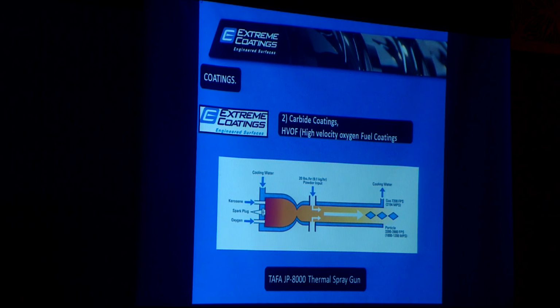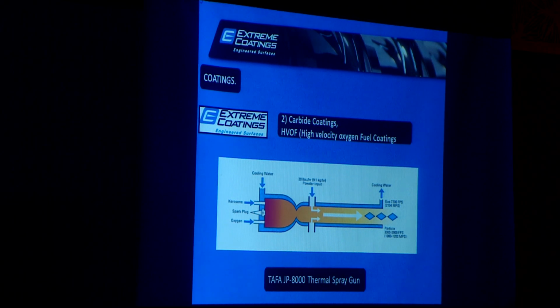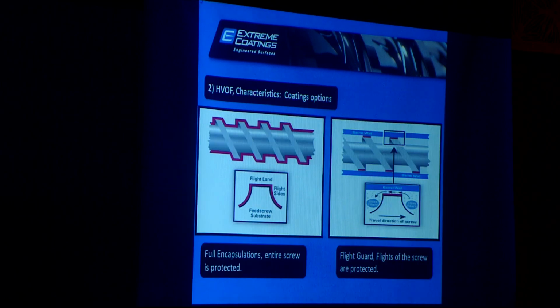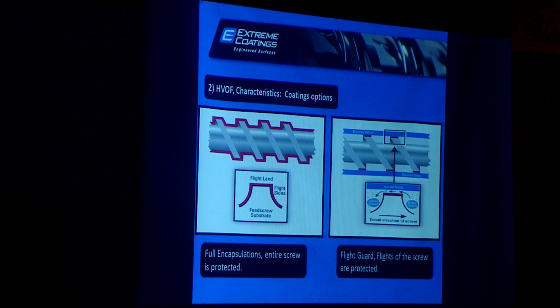So this is what we do as an extreme coating. We have a technology by which we put tungsten carbides on the entire screw surface area. That means on the OD as well as on the root diameter. What are the benefits of it? Two things. First, unlike other bimetallics which can protect only the flight top, we can protect the entire screw. That means all four kinds of wear which industries have, that is adhesive, abrasive, corrosive, and erosion, can be addressed with one solution.